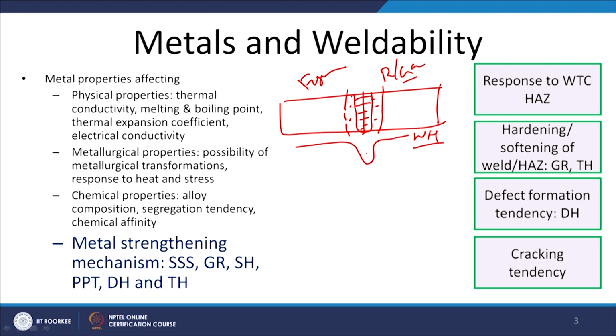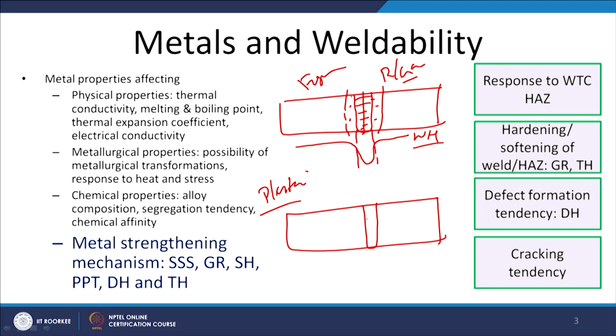So, the heat affected zone as well as the weld zone, both are softened significantly like this. But if we are using the plastic deformation based approach, then certainly we will have the opposite effect, because the joint interface will be formed through controlled plastic deformation, and so the zone which is experiencing the controlled plastic deformation certainly will offer the greater hardness. And then next to that zone, the region experiencing the heat generated during the plastic deformation based processes will experience softening, primarily due to the loss of work hardening effect. So here we may find a drop like this.